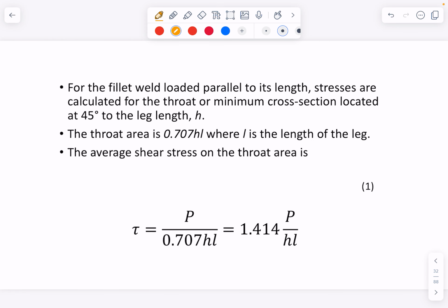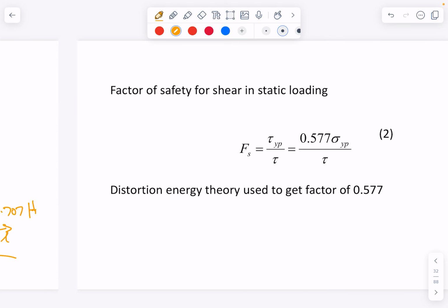So if we look at a fillet weld loaded parallel to its length, stresses are calculated on the throat. This is the image a couple back. So I hope that's fairly clear that, again, we've got the H, 0.707 H to get the width through the weld, and then times L. So we end up, again, 1/0.707 is 1.41. So that's pretty straightforward.